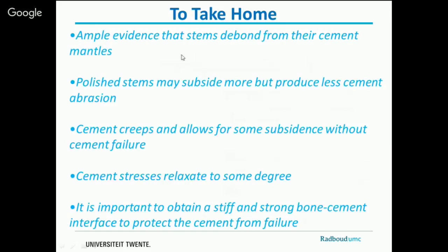Okay, this is my last slide. So we know that stems debond from the cement mantle. Polished stems may subside in the cement mantle, but perhaps produce less cement abrasion. So subsidence itself is not such a problem. We know that cement creeps and allows for some subsidence without cement failure.